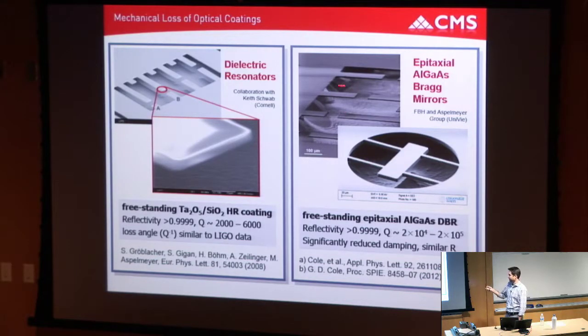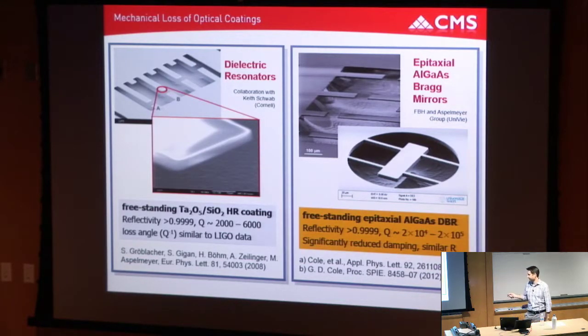So we made a variety of, again, the same sort of one-to-one bridge and cantilever structures, and then also some more advanced devices to reduce coupling losses from the clamps to the surrounding environment. We were able to push the Qs up, at cryogenic temperatures, I think the highest we measured was in the 250,000 range. So it was a nice improvement over what we saw here. Unbeknownst to me, there was a whole other group of people that cared, like I showed, the optical clock people and the gravitational wave folks. They saw this result with a 50 micron mirror, and they said, can you deliver me various optics from NIST scale to LIGO scale?